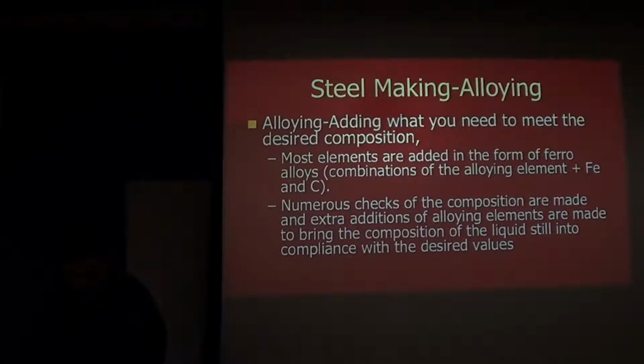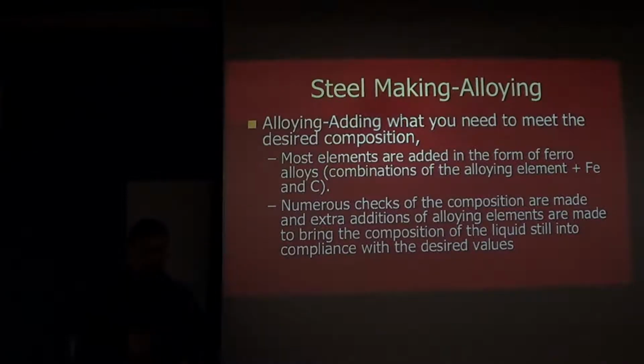So we get rid of everything we don't want, and now we are going to need to put in what we do want. So if we're making a plain carbon steel, there's not much to be added. A little bit of manganese, and that's probably about it. Maybe a little carbon, because you've probably taken the bath of liquid metal to nearly zero carbon, and then you'll add in what you need, because carbon is really cheap and it's simple to add.